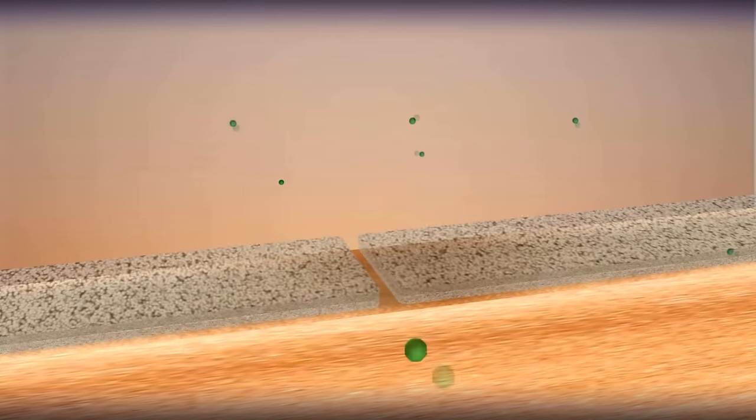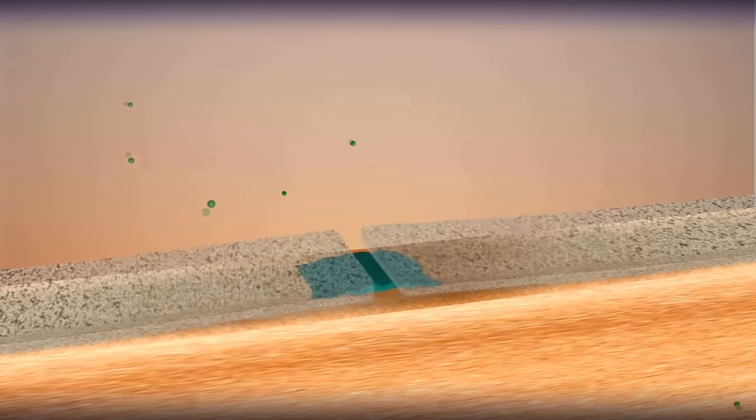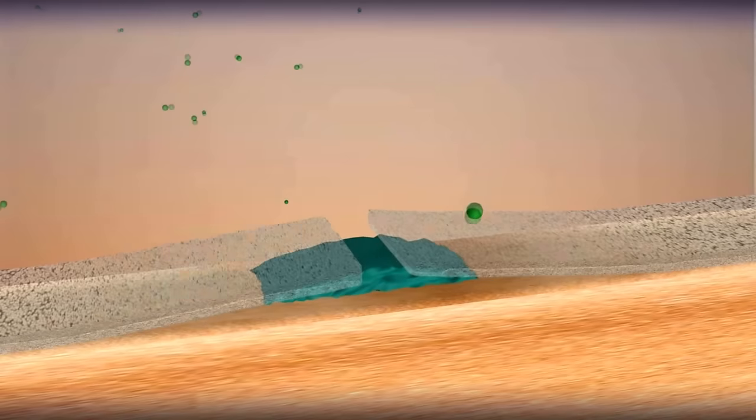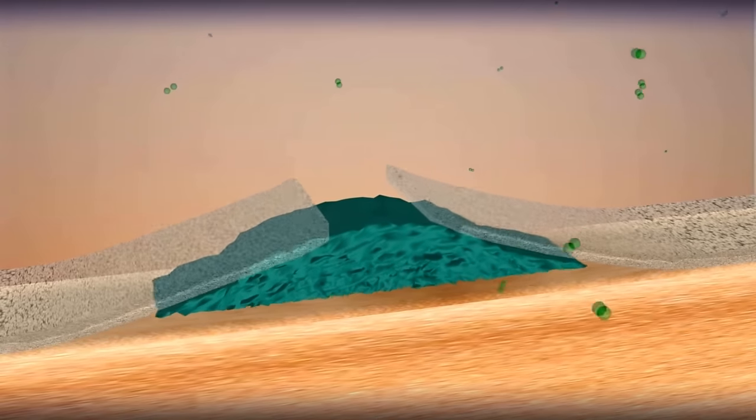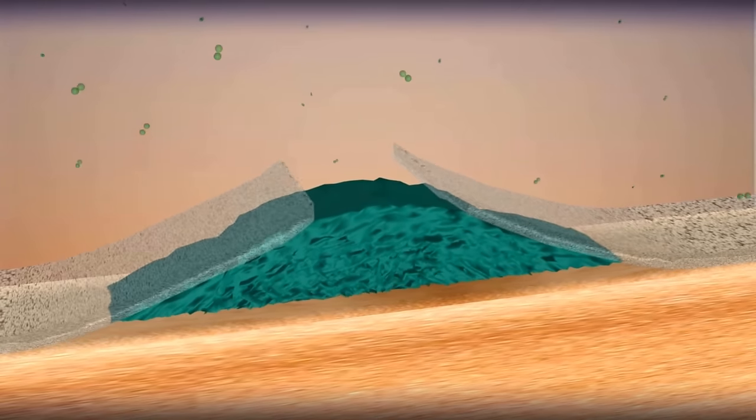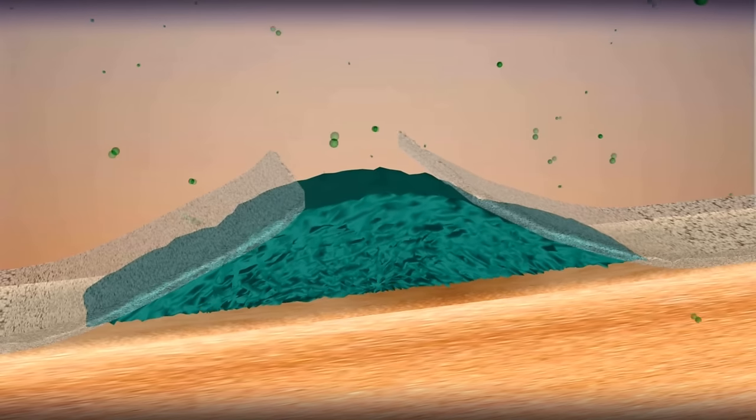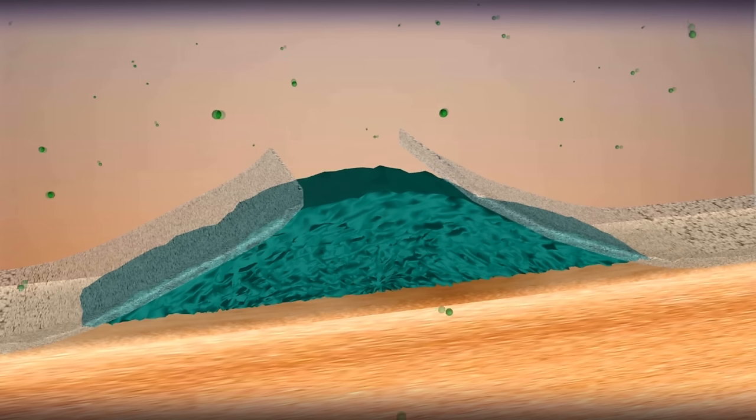The large area graphene had small defects, allowing chloride ions to reach the metal substrate. As a result, corrosion products started building up under the graphene, lifting the coating and exposing even more of the metal substrate that we wanted to protect.